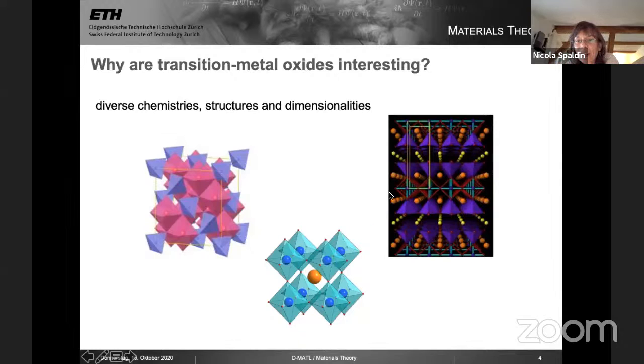Maybe you recognize this structure on the right. This is the prototypical high-Tc cuprate superconductor, which is a layered 2-dimensional compound. The transition metals in this case are at the center of these coordination polyhedra, which are square pyramids. So again, another kind of local structural motif around the transition metal. Again, the oxygens are the little red dots here.